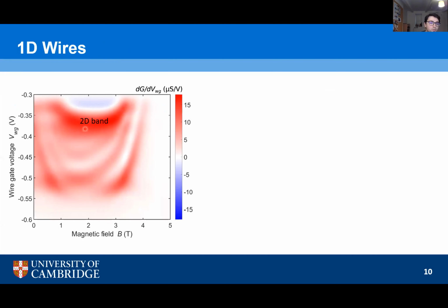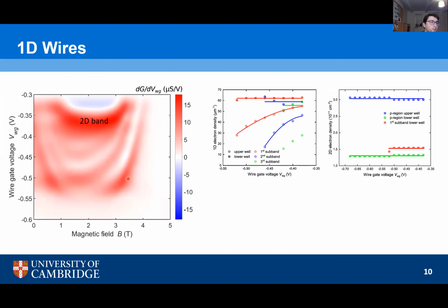So here you see the 2D band, and once the voltage becomes negative enough, you start seeing multiple 1D subbands, anywhere from 3 up to 4. Of course, by changing the geometry, you can change this number. We've fabricated a device up to 7 subbands, 1D subbands, that is. From here, you can extract densities, both 1D and 2D.